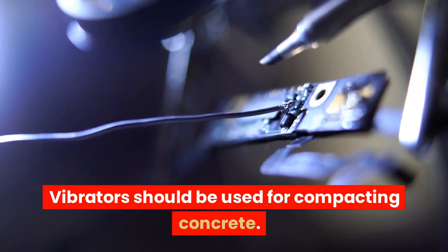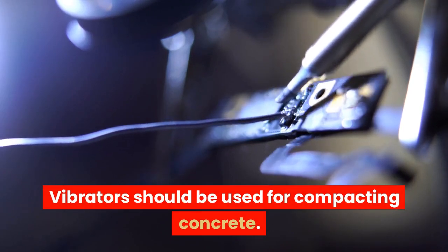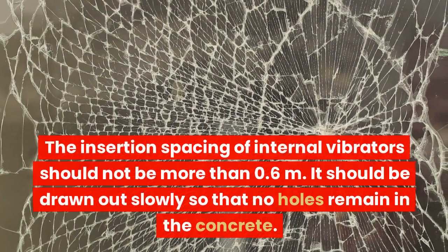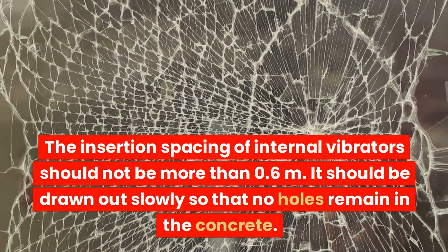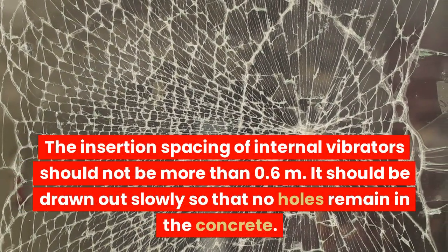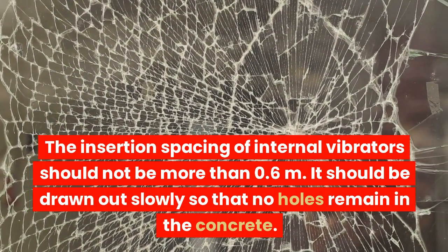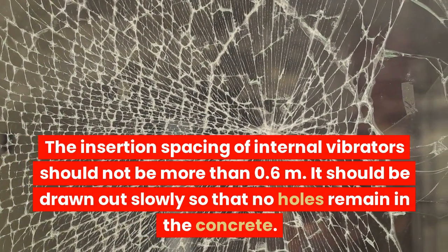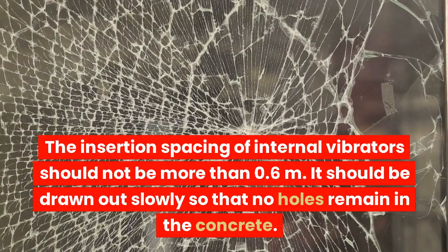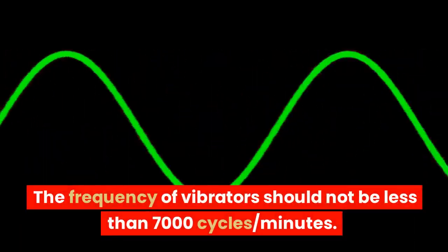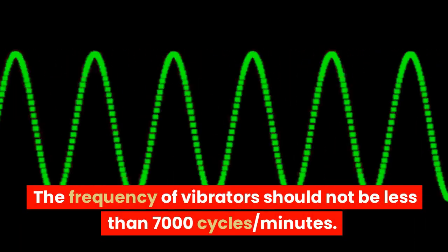Vibrators should be used for compacting concrete. The insertion spacing of internal vibrators should not be more than 0.6 meters. It should be drawn out slowly so that no holes remain in the concrete. The frequency of vibrators should not be less than 7,000 cycles per minute.